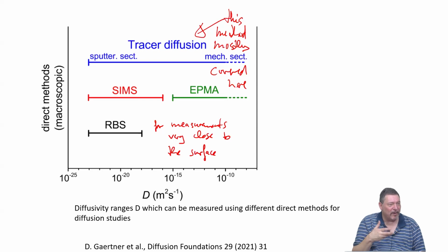And so it means that very rapidly you can then run into a situation where your counting efficiency is not sufficiently high to really recognize tracer or tracer profile over a certain depth. The tracer lifetime is one thing, but also the efficiency of the decay should be high. So it means there should be in the tracer enough activity so that you have enough decays per second so that the detector can give you a decent count. Otherwise, you have to wait just too long.